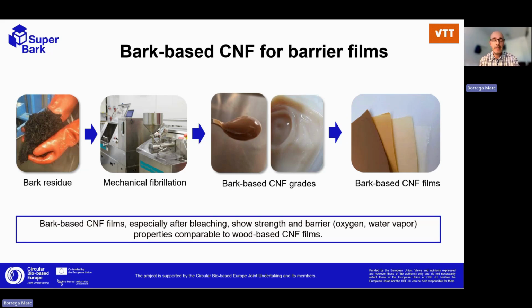This is done by VTT. VTT has a lot of experience in making this type of film from nanocellulose. This is quite interesting because you can also tune the color of the films. They look quite nice depending on the polyphenol content. We have also measured barrier properties and strength properties, and basically what we see is that they have properties comparable to those you would get if you make a film from wood-based nanocellulose. So I would say that in that respect, having this bark-based nanocellulose film does not bring any performance advantage, but it has the advantage of using bark as a side stream rather than using the wood pulp.